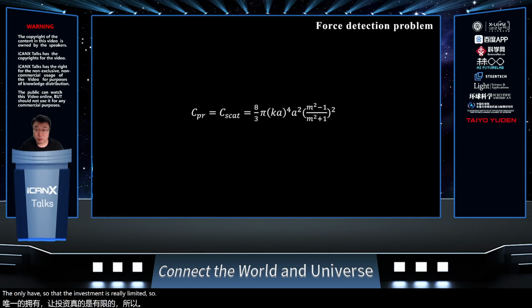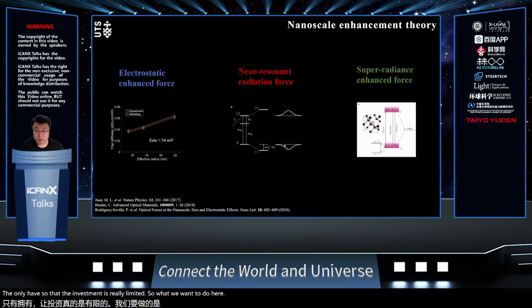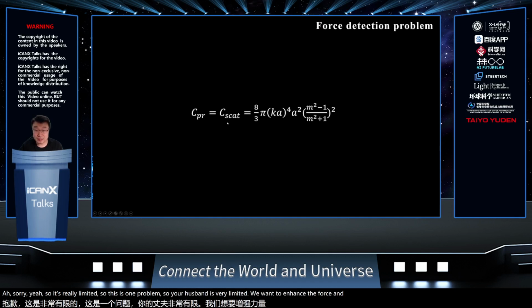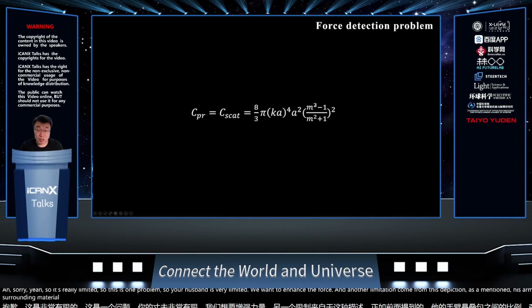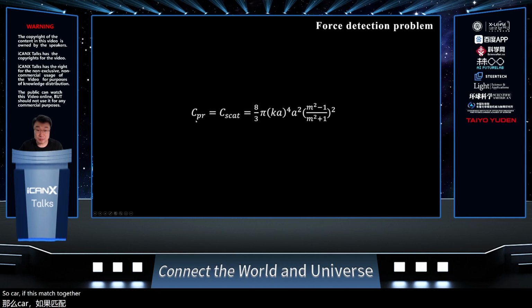So this is one problem: the enhancement is really limited. We want to enhance the force. And another limitation comes from the detection. As I mentioned, this m is the ratio between the refractive index of the particle and the surrounding material. If these match together, your scattering is really, really low. You couldn't even detect your force.